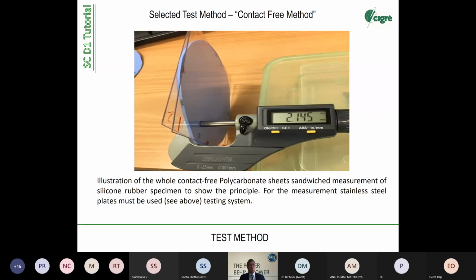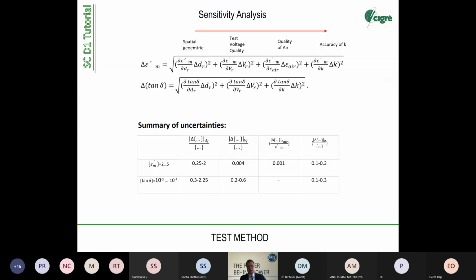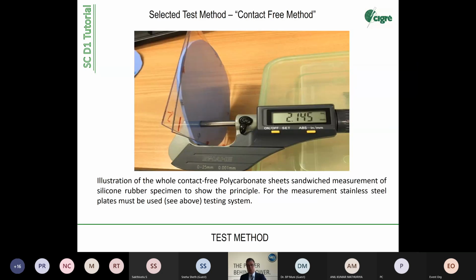What you do in the round-robin test, you don't rely on one sample, and you should not rely on one sample. One sample is no sample. In this sensitivity analysis, Professor Oliver also investigated the influence of the number of samples. You can bring the error for each element down significantly by measuring 5, 10, or 20 samples. Okay, if we measure 100 samples, we have a low error, but maybe not economical anymore. So we have to find a good compromise. For this round-robin test, a sample number of 5 was good. I think for later practical applications, you will not measure 5 cable slices or 5 cable samples because you cannot afford to do it, or you have not the time or not the resources. So this is one thing we have to look at. We have also recorded it in the lessons learned.